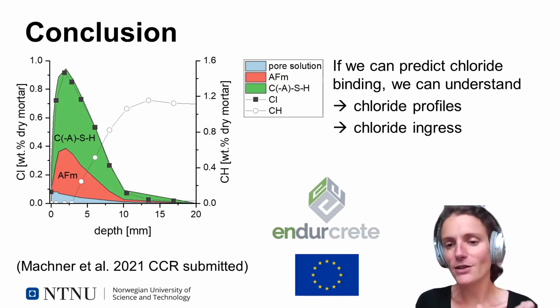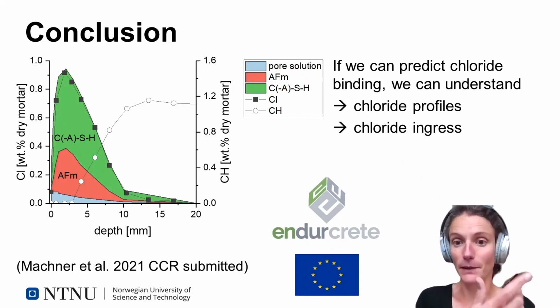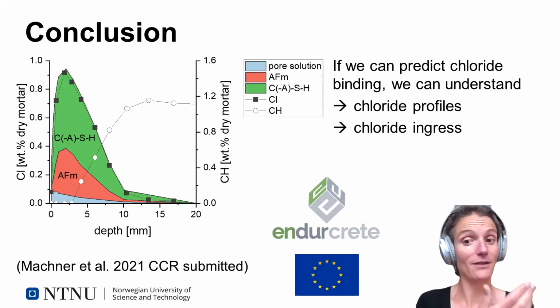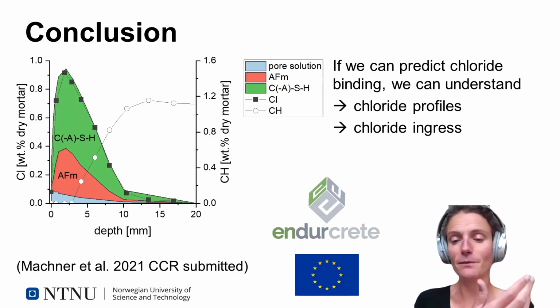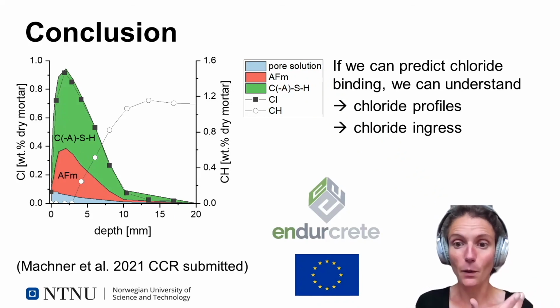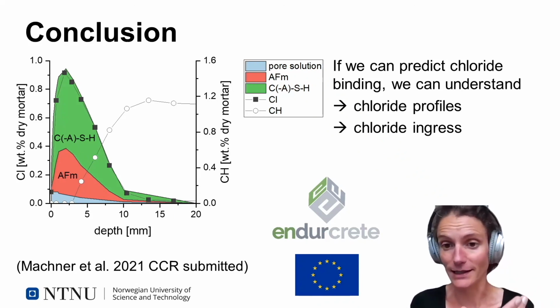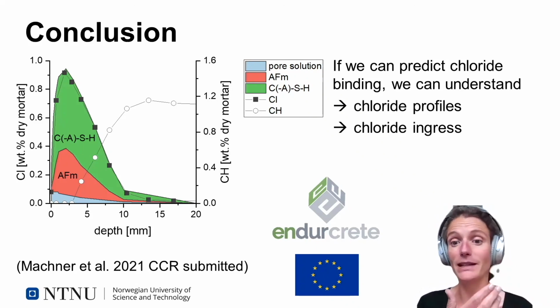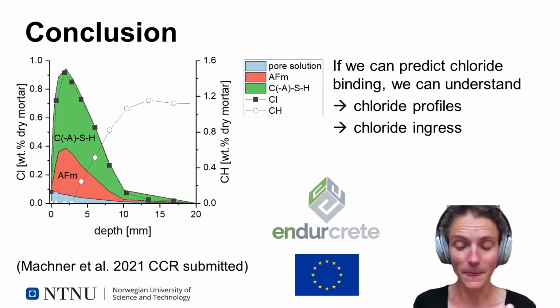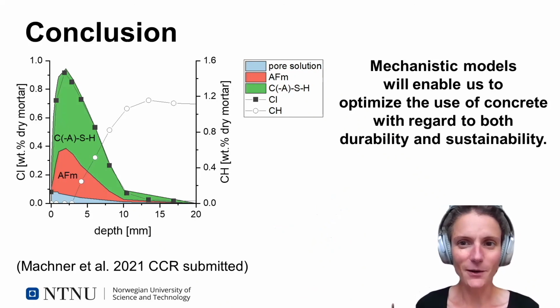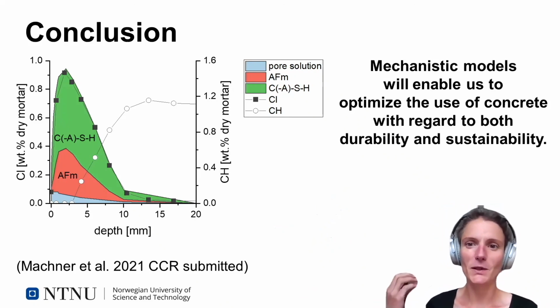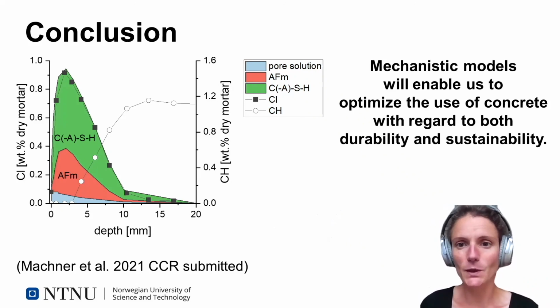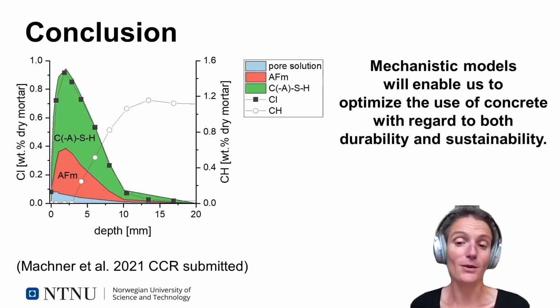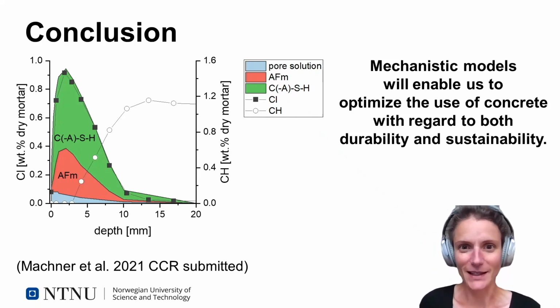So what this figure shows is that if we understand chloride binding, here it's measured, but even better if we can predict it, we can better understand chloride profiles, why they look the way they look, why they change because we're adding SCMs. And this will be a great step forward to understanding chloride ingress with concretes with new binders. So in a way the overall goal is to work towards mechanistic models which we can use to optimize concrete, both with regard to durability and sustainability. We can actually get the best out of this wonderful material.